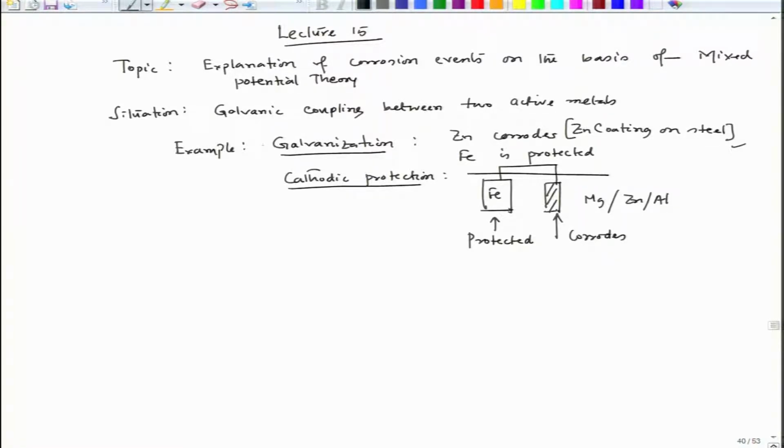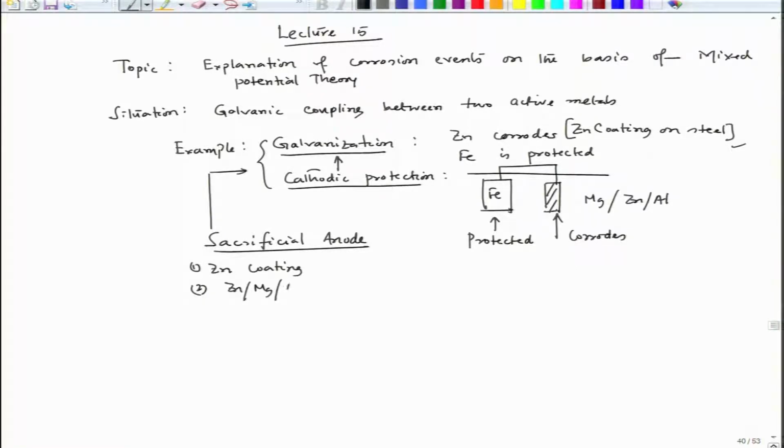Now this kind of situation we call cathodic protection. When one electrode corrodes and the other electrode is protected, this is the kind of cathodic protection where we use a sacrificial anode. In the first case, the zinc coating is the sacrificial anode, and in the second case, zinc, magnesium or aluminium are rods or some other shapes. So these are examples where we experience a corrosion event which is the galvanic coupling between two active metals. Why? Because iron is active, zinc is active, magnesium, zinc, aluminium, iron, all are active,